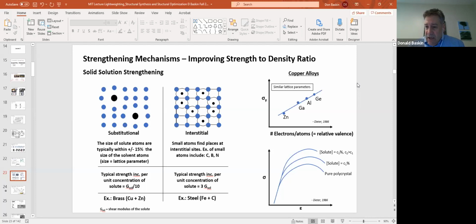On the right here, there are a couple of graphs that show that the amount of increase in yield strength, and the amount of solute material that can be absorbed by the base material, is a function of the electron structure of the solute atom. And the one at the bottom shows that, for example, with a steel, as you add more and more carbon, the strength goes up. You may decrease fracture toughness, that is the ability of the material to contain a crack within it without that crack propagating, but the strength has gone up. The more carbon you add, the stronger it gets, pretty much. There's a limit, obviously. There's a solubility limit. You can't just keep adding carbon forever.